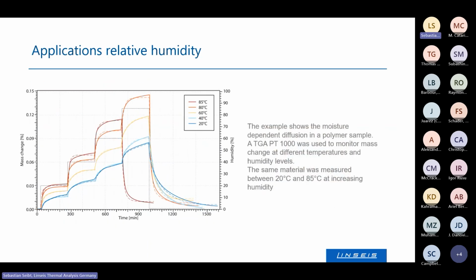Another example that I can show, that we did by ourselves for another customer who was interested in the system, was more or less the moisture-dependent diffusion into a polymer sample. That experiment was done on a TGA PT1000 system that was used to monitor mass changes at different temperatures and humidity levels. The same material was used here multiple times between 20 degrees and 85 degrees at increasing humidity levels.